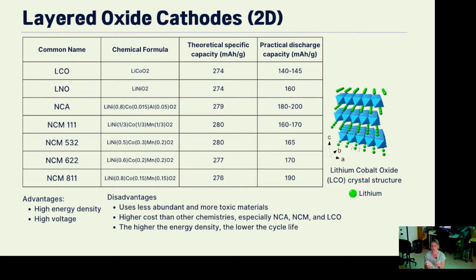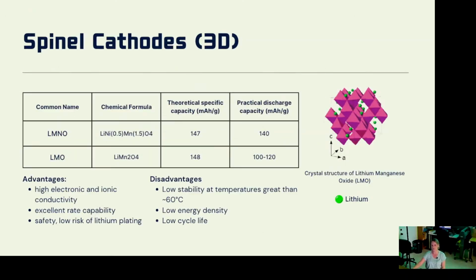LCO, lithium cobaltite, is often used in cell phone batteries. They're great. They work well, and it's 2D because lithium will move in planes. So you see the green dots are lithium in that diagram. For spinel cathodes, these are 3D cathodes, and these are the fastest rate capable ones because the lithium can move into these materials in 3 directions. However, they have a lower cycle life and lower energy density. These are lithium manganese oxide materials.